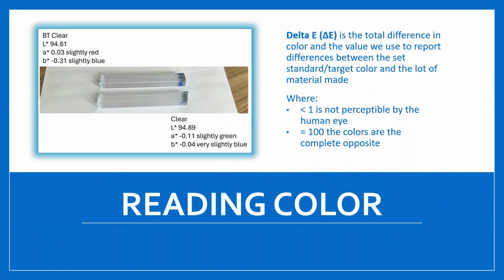And so again, LAB. But now what we do is those would be our target values. So when we compare something, we make a new lot, we make our first lot to make sample chips for you to look at, what have you. If you've heard the term delta E or change E, it is going to be the total difference of color. So instead of just giving you the target LAB values and then giving you the LAB coordinates of what the part tested at when it had been checked for color, they'll give you a delta E. And what that does is it takes a comparison of all of the differences. So it takes into account the difference in the L space, the A space, and the B space, and then compares it. And so generally you'll get a delta E value of wherever it ends up being, and that's comparing our total shift.